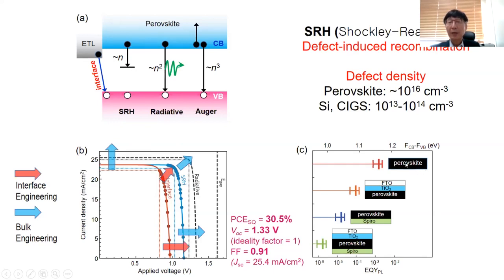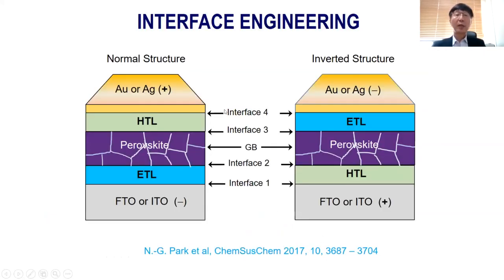So the perovskite itself can show a high open circuit voltage. However, if you add some interfaces, if you increase the interfaces, then you expect a gradual decrease in open circuit voltage. So the interface is very important. There are so many interfaces in both normal structure and inverted structure that you have to consider every kind of interface, including the grain boundary of the perovskite.